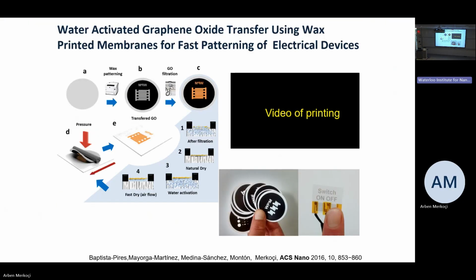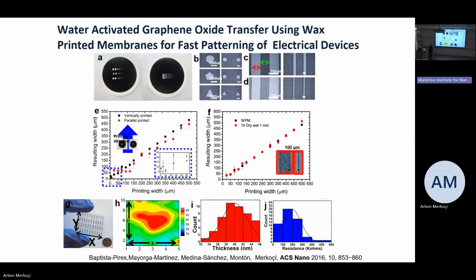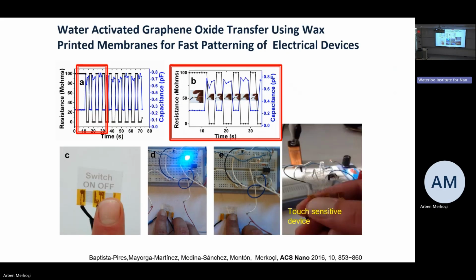And also, as I mentioned, graphene for us is one of the most important areas of research. We stamp graphene oxide suspension after filtering. We can stamp to any kind of surface using some wax printed membrane. So we control, of course, the quality of the stamping, the printing width, and of course, resistance, thickness. And after having this control, we are able to print to any kind of surface.